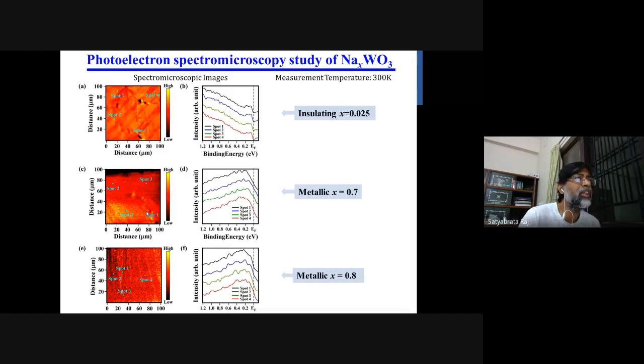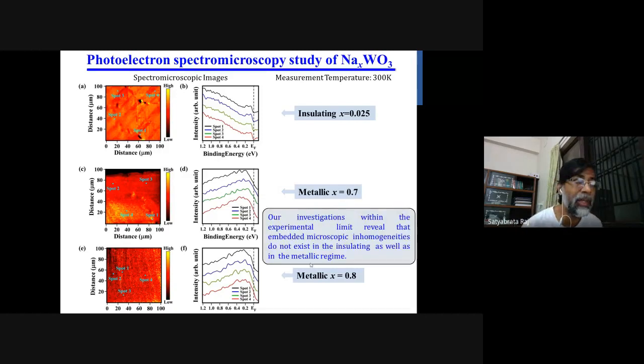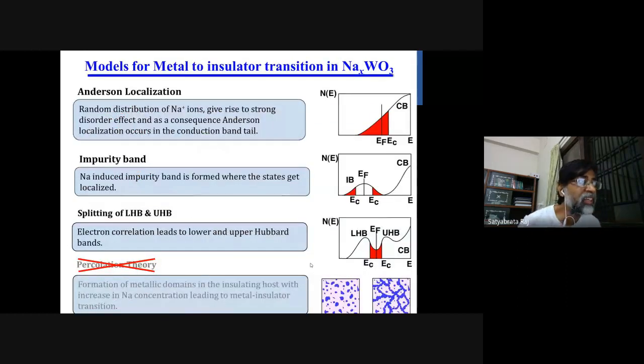So our conclusion is that our investigations, within the experimental limit, reveal that embedded microscopic inhomogeneities do not exist in the insulating as well as in the metallic region. So this discards the percolation theory in the context of NaxWO3. Now these other 3 models still exist. We have to see which one fits best to explain our metal-insulator transition.